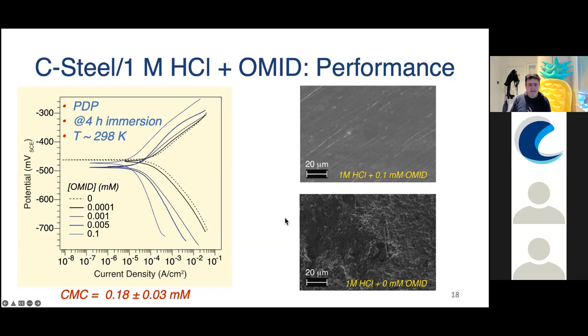These show potentiodynamic polarization curves. And just to note, the critical micelle concentration in this case is approximately 0.18 millimolar. So in these data here, we're going up almost to our critical micelle concentration.